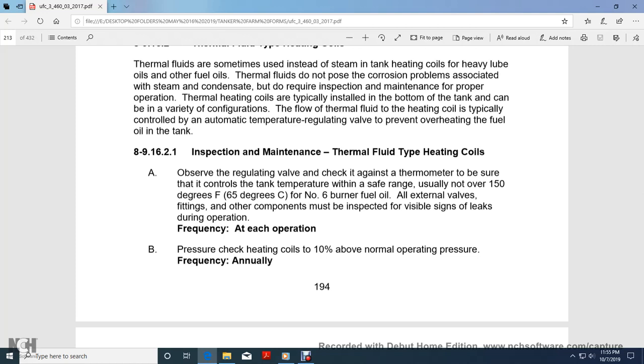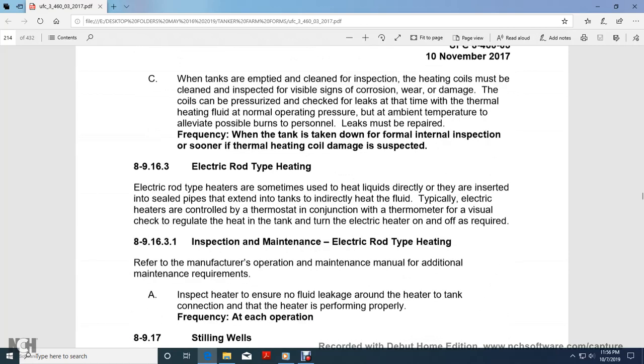Inspection and maintenance of the thermal fluid type heating coil: observe the regulating valve. Check it with the thermometer to verify that the control keeps the tank temperature in the safe range, usually not over 150 degrees, for number 6 burner fuel oil. All external valves, fittings, or other components must be inspected for visible signs of leaks during operation. Each operation, pressure check the heating coil at 10% above the normal operating pressure.